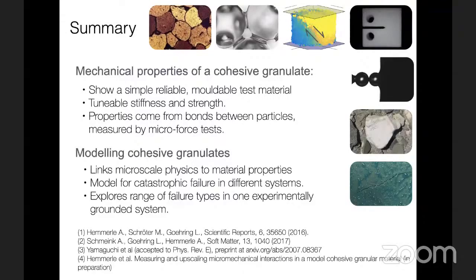From the measurements that we've made of that, we've informed a numerical simulation which can reasonably accurately, it's slightly stiffer, but we think we know the reasons for that, predict the way in which these materials deform and fail, and also allows us to explore other things which are not accessed experimentally, including, for example, differences in volume fraction.